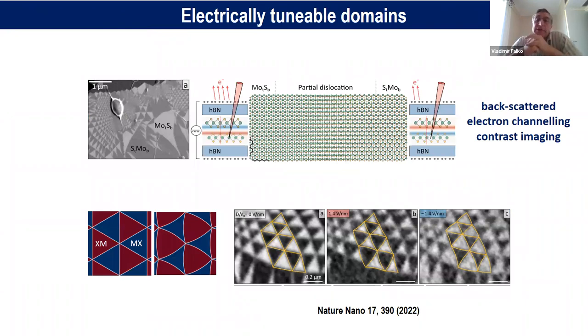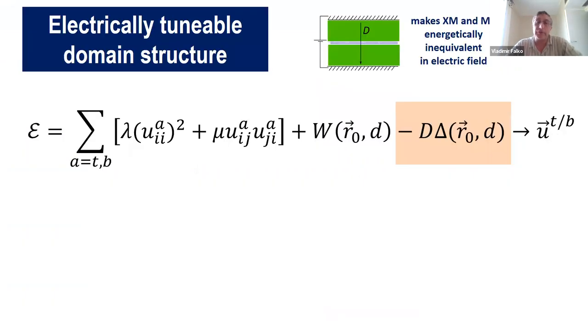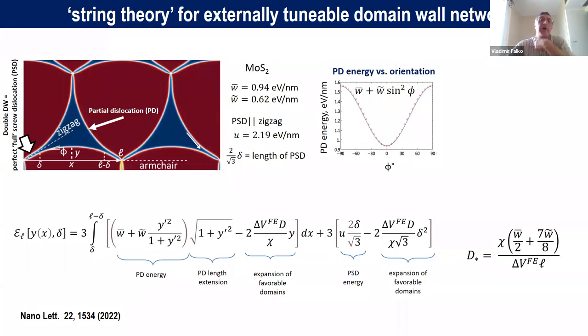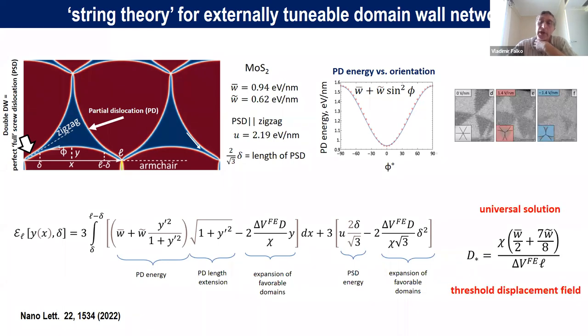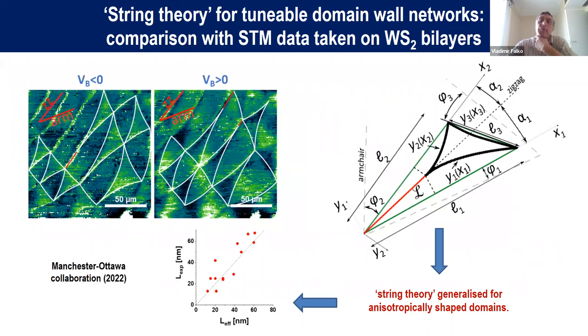It also can be tested in a different way. One can apply an out-of-plane electric field and start changing the shapes of the domains. And when one changes the shapes of the domains, one can start moving the domain walls. And we developed a bit of physics, a bit of theory to describe the variation of the structure, even merging of individual partial dislocations into full dislocations. And this has also been tested by the observations of the variation of the shapes of the domains in various ways. In particular, this experiment is a recent measurement produced by the Ottawa group, where they see this change of the domain wall shapes produced by the locally applied electric field.